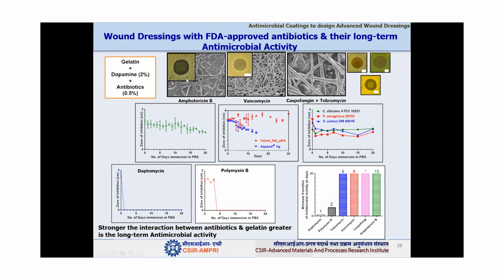A little bit of explanation I want to give here. This is a diffusion picture, and this yellow color is actually bacteria. You can see here that where we have put the wound dressing material, there is no bacterial growth. That means this material has antibacterial properties. In the same way here also, where the material is available, there is no growth of this yellow color bacteria. And even in this case, for gram positive, gram negative, as well as the fungus, there is no growth of these microorganisms. That means these nanofibrous wound dressings have very good antimicrobial properties.